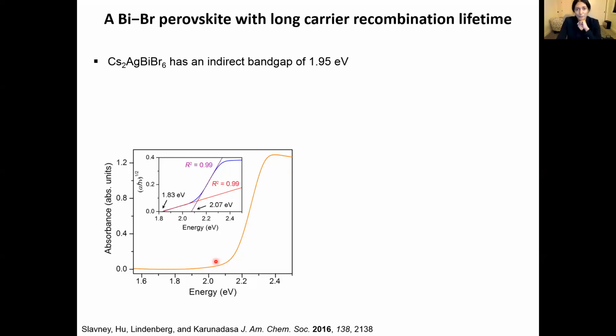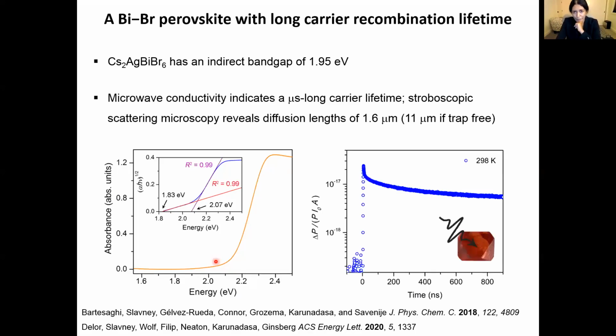So we did a whole bunch of spectroscopies. I'm not going to go into technical details in this talk, but feel free to ask me questions at the end. And we find that this material has really long-lived carriers that can diffuse very long distances. So this is really good news, and it tells us that if someone were able to make a micron-thick layer of a double perovskite, this material should be an efficient solar absorber. To date, no one has been able to make this thick layer. This is an ongoing challenge.